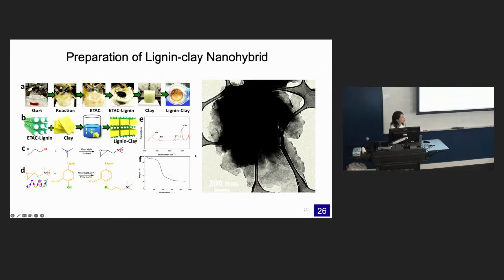Here you can see our nano-lignin clay hybrid. The size is about 200 nanometers. Firstly we synthesize quaternized lignin, and then with the anionic clay together, they insert to form an exfoliated nanohybrid structure. It looks like a gel-like structure. And the second step, as we mentioned before, we combine with the agricultural residue-based bio-based polyurethane together, and they encapsulate the urea inside.